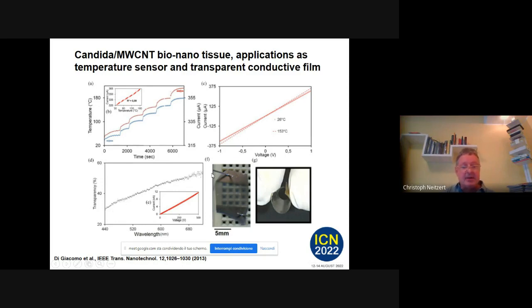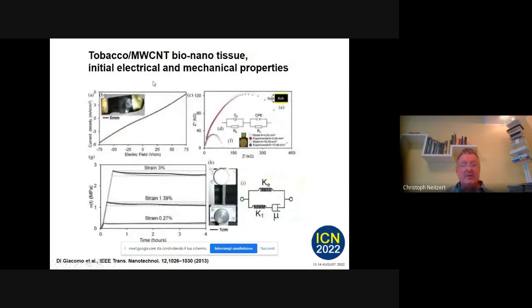And that is the transparency. This was 40% transparent. Here you see it. You can fold it. It's a bio-nanotissue which is foldable, and it's transparent, a lot of interest, and you can use it even as a temperature sensor up to high temperatures. Then the next one we used was made of tobacco.